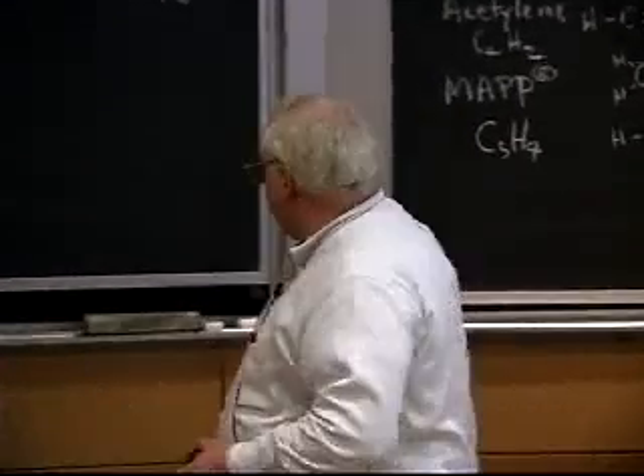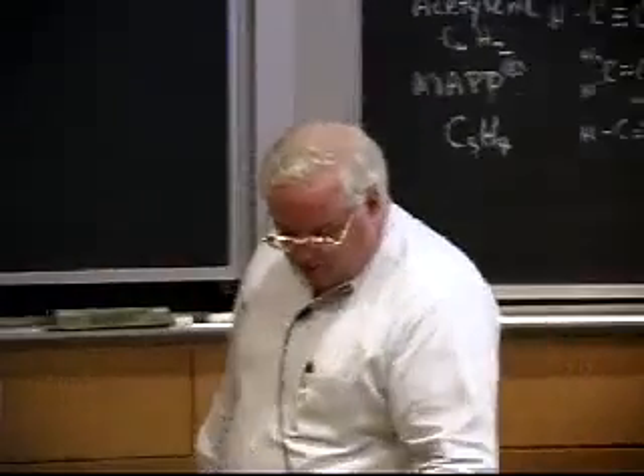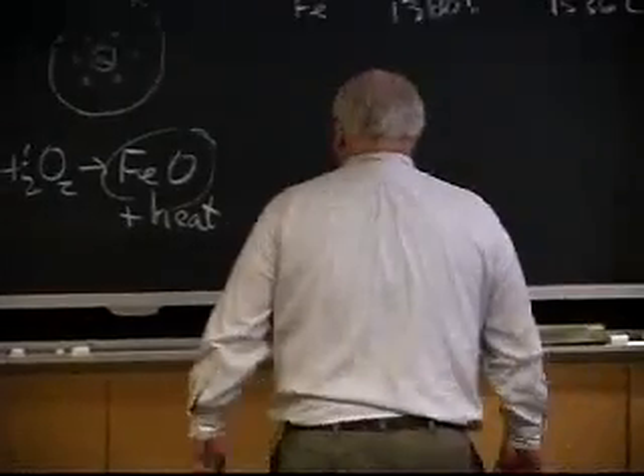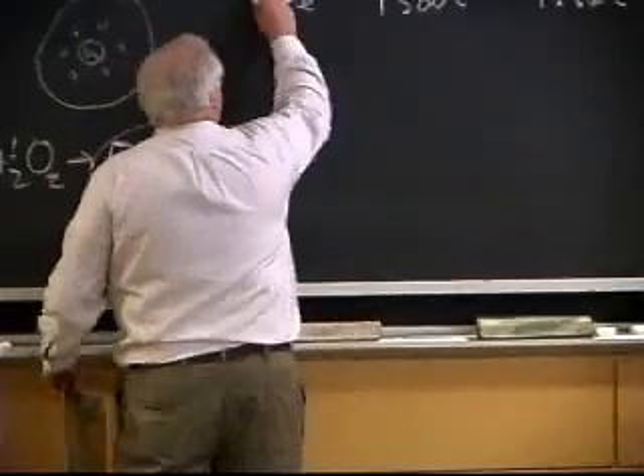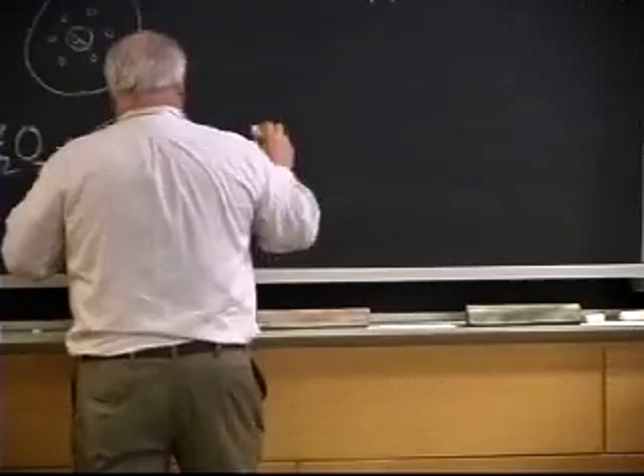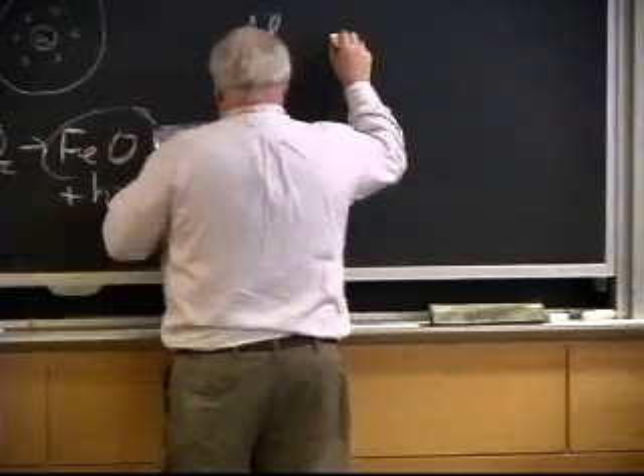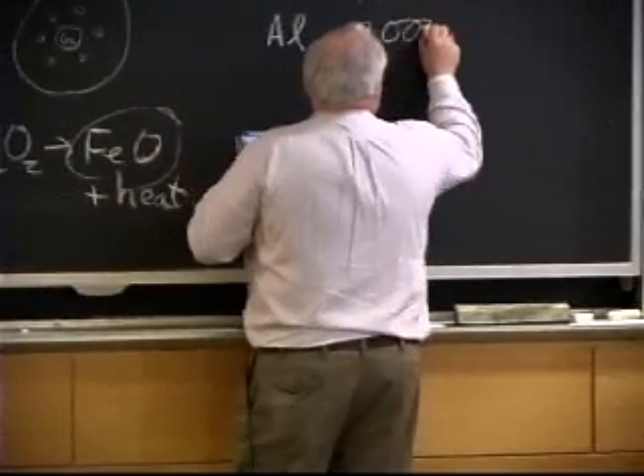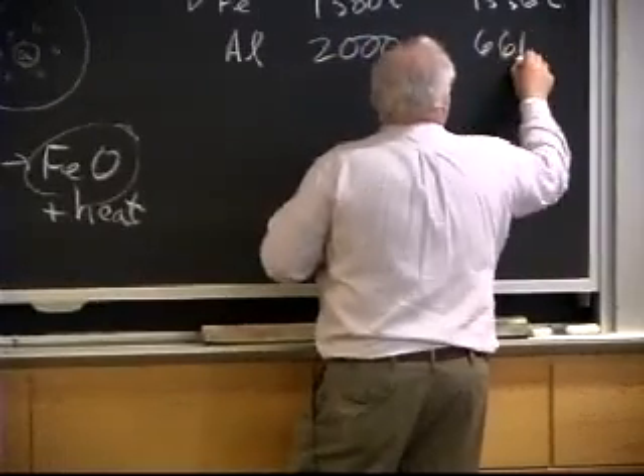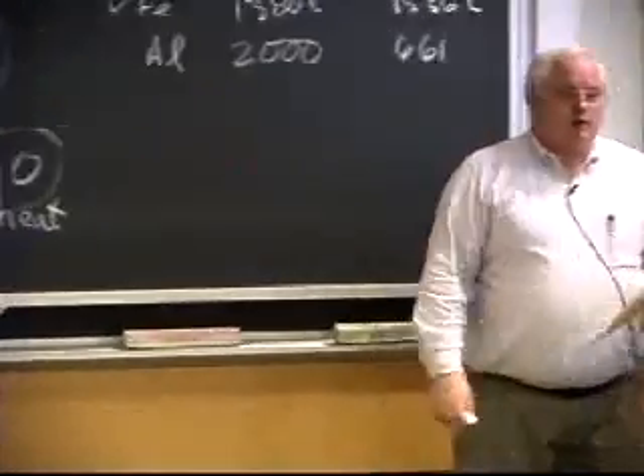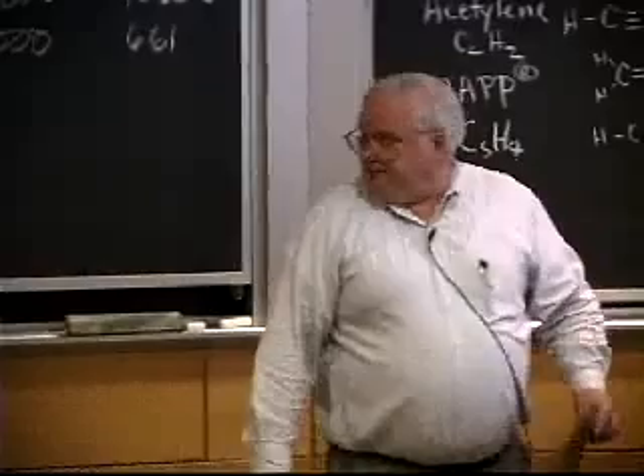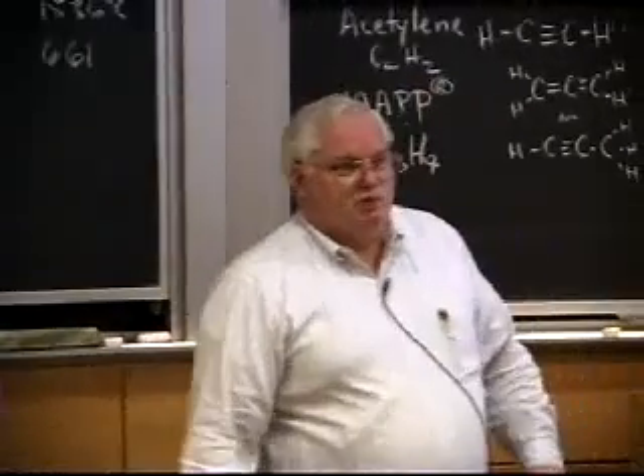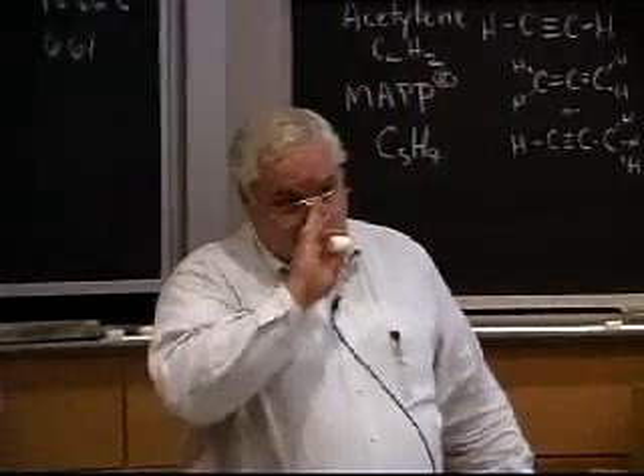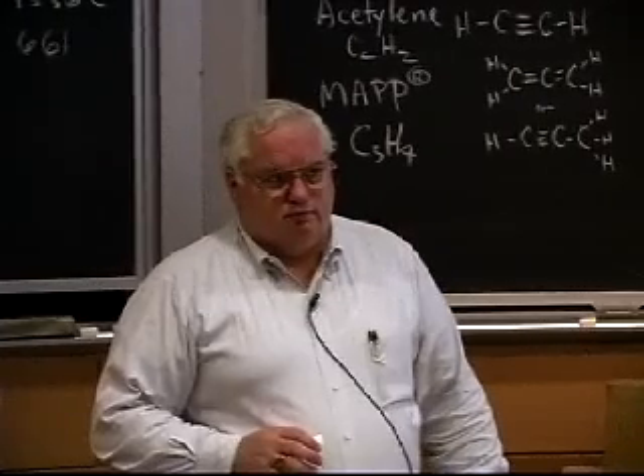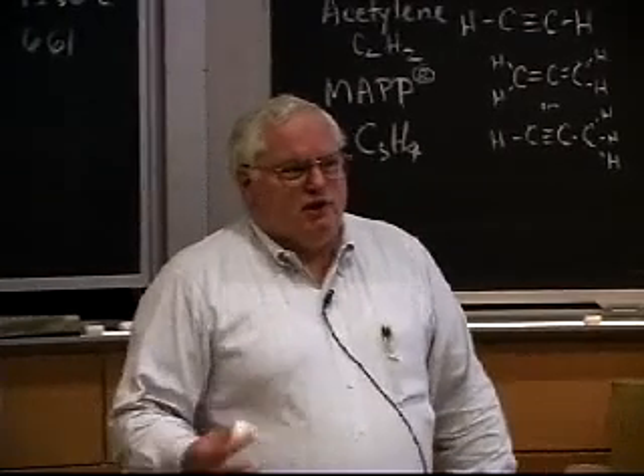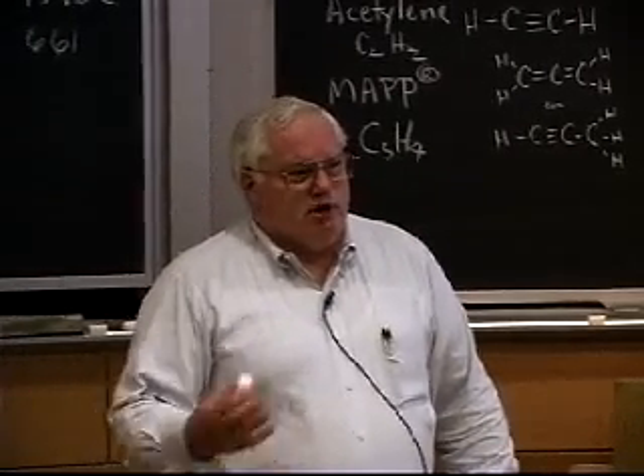Now, it turns out there are other metals that you can flame cut. Well, actually, there are not. But you can flame cut iron, and that's good. Aluminum, it turns out, we have some problems. The melting temperature of aluminum oxide is 2000 centigrade, and the melting temperature of the aluminum is 661. You cannot flame cut aluminum. What will happen is you'll melt the aluminum underneath before the oxide breaks up and exposes fresh aluminum.